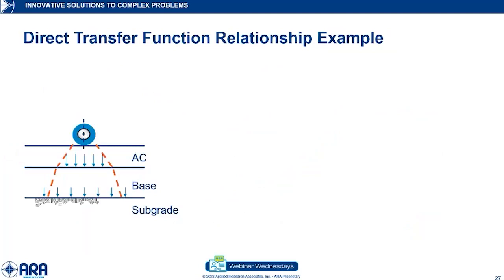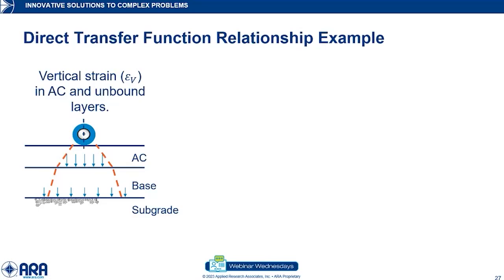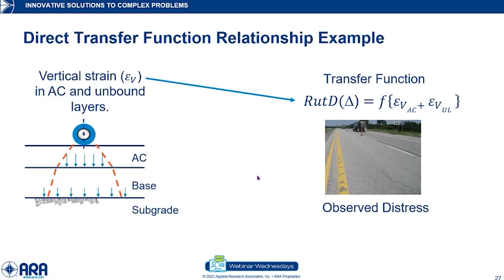Now, one exception to the rule, and this isn't critical to remember, but I'm presenting it anyway, would be rutting in the asphalt and unbound layers. The mechanistic response here is vertical strain. More specifically, we're interested in the plastic component of the vertical strain. Again, this is simplified. There are a few other things happening here, but we're bypassing the intermediate material law and damage accumulation. We're going straight to a cumulative rut depth or deformation measurement based on these plastic strain components, adding them together for each of the layers.